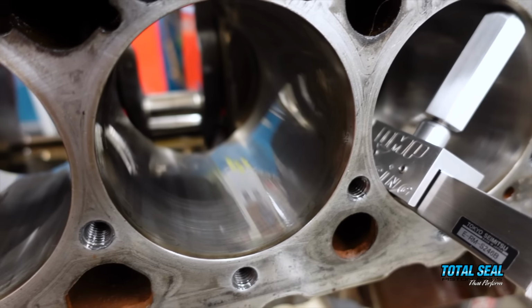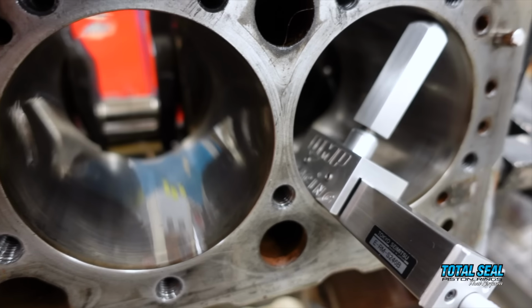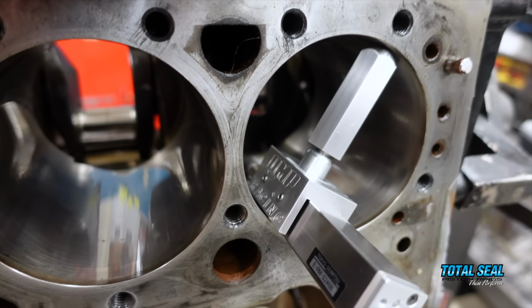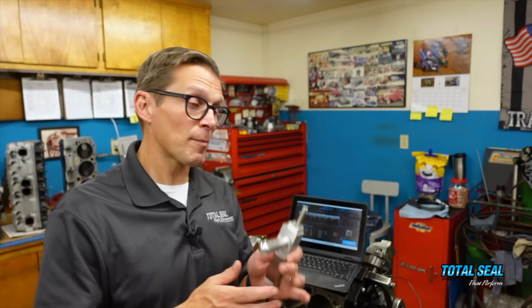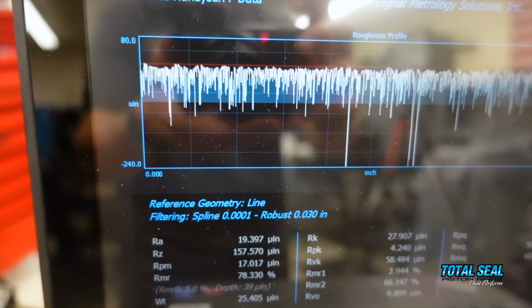If so, that may have changed their results. What we did with this engine is we used a profilometer to measure the results. We did that plateau hone that we know works well for these thinner steel rings, which by the way, also works well for the thicker old school ductile moly rings. That's the nice part about the plateau hone technique, is it works for both old school type rings and the modern new school rings. It works great for both. That's what we have in this engine. The profilometer results show us that. So that may be one of the things that changes the results of our test compared to their test.